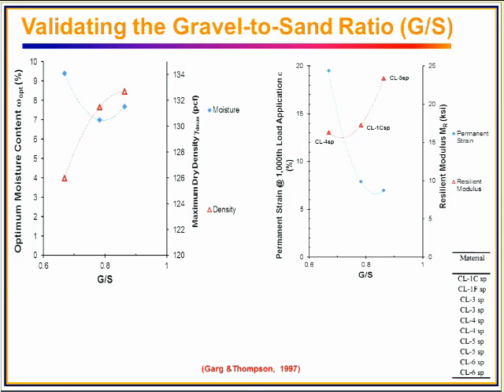Can you explain, you said there was no trend between resilient modulus and permanent strain? As you can see, the permanent strain decreases with the GS ratio, but at the same time, the resilient modulus is increasing with GS ratio. So there's a relationship between permanent strain and resilient modulus, but not with GS ratio in between. Is that right? Can you repeat? You said the permanent strain and resilient modulus aren't related, but it seems like they are related in that case. I assume you're testing the same aggregate: if it has higher permanent strain, it has lower resilient modulus, irrespective of the GS.